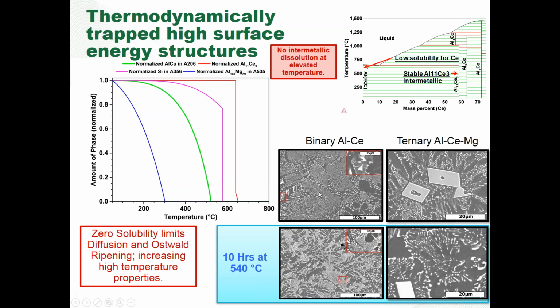And so we have some good-looking microstructures here in the binary aluminum cerium alloys, and a ternary aluminum cerium magnesium alloy. People ask me about these big phases in here. Well, the phases are not that big. The scale bar is a little different on the aluminum cerium magnesium. That's a 20 micron scale bar, and the top is as cast, and the bottom is 10 hours of exposure at 540 degrees C. So at temperatures that high, you have some homogenization of the aluminum cerium structure, as you do with the magnesium, but the magnesium actually stabilizes that a little bit. So you don't have any growth, you don't have any coarsening, it doesn't disappear, it's still all there after exposure for a long period of time.